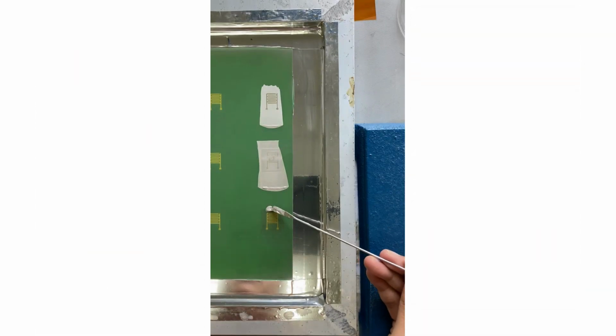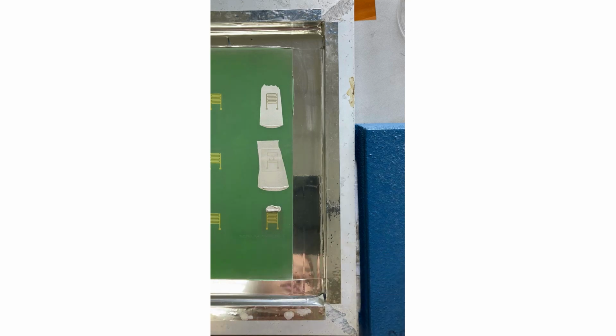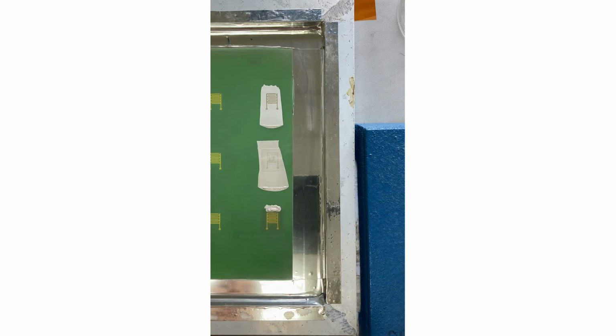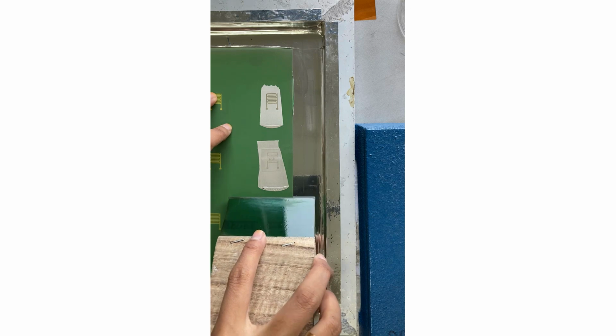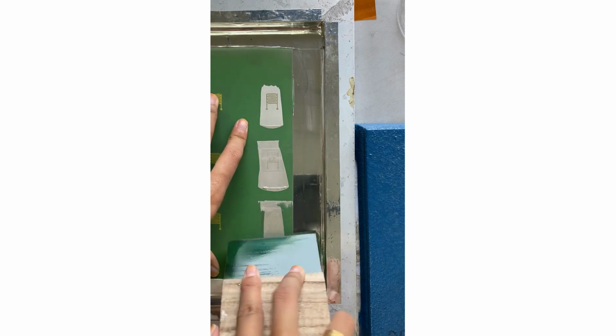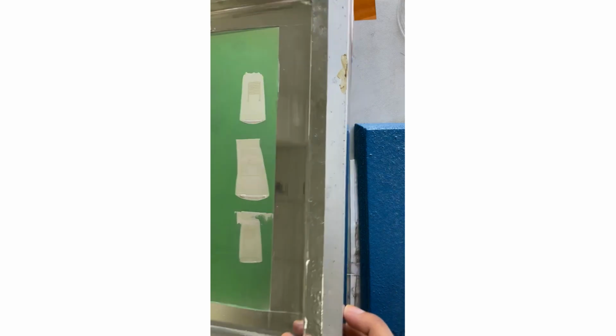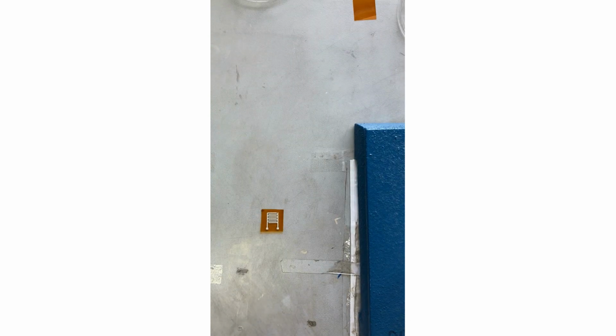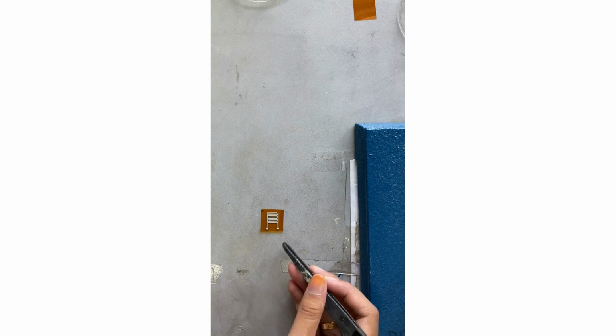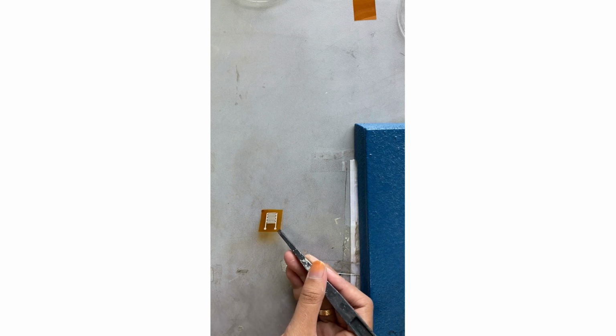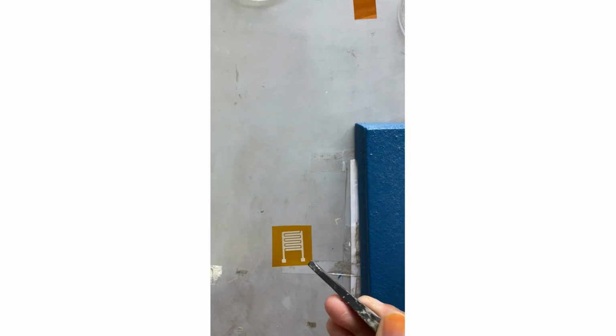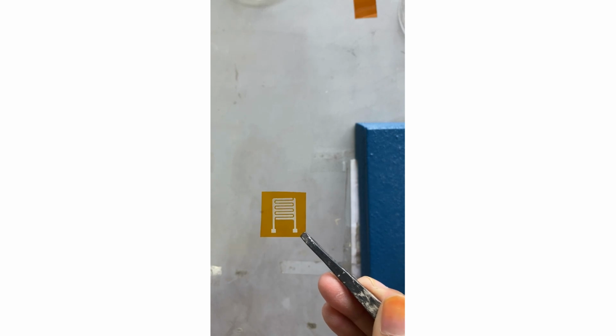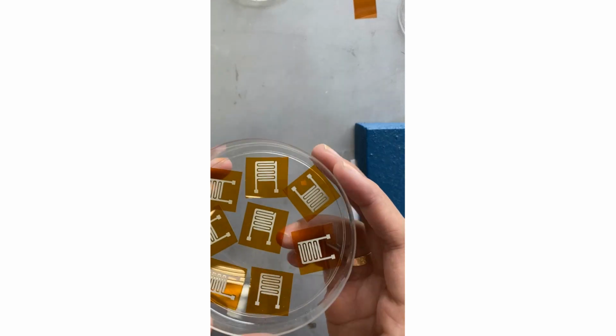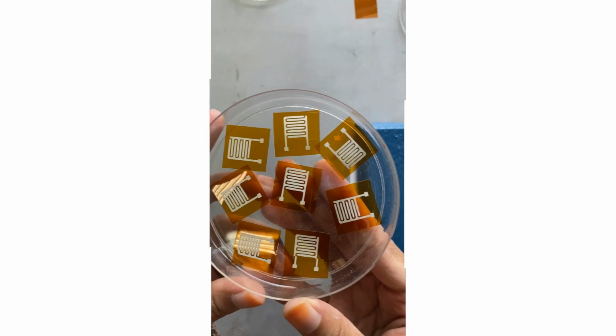Kapton film was used as the substrate of the gas sensor. The interdigital electrode was deposited onto the Kapton substrate by using a screen printing technique. Firstly, an amount of silver paste was placed into the frame, then the paste was scraped across the screen surface using a squeegee. Squeegee pressure transfers paste material onto the substrate by following a pattern on the stencil. As a result, the design is transferred to the substrate and the paste layer is deposited. The electrode was then annealed at 150 Celsius for 10 minutes in the oven.